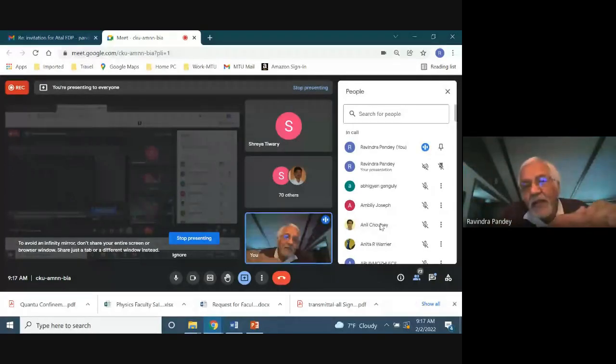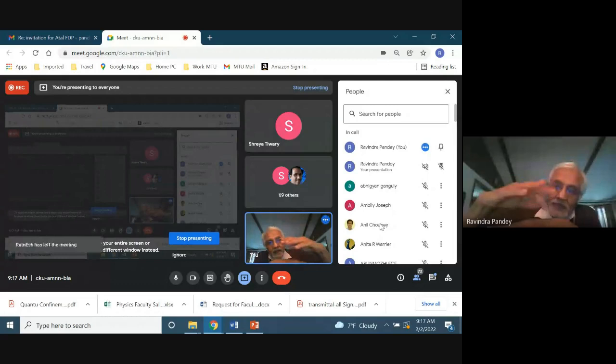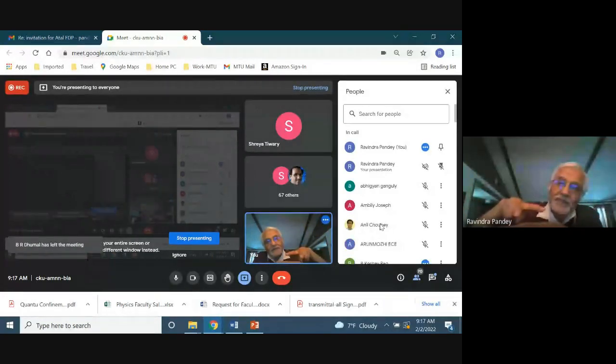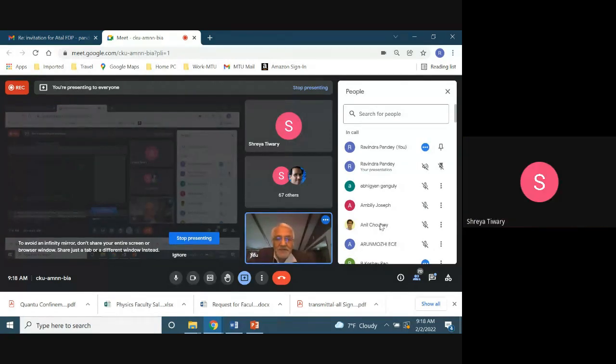And for graphene, being carbon again, in the monolayer you're going to have a zero gap, and BN has a finite gap. When you combine them together, there is this electronegativity difference, or difference in bonding. One carbon is looking at boron, the other carbon is looking at nitrogen, so they experience a dissimilar electronic structure. They're going to behave a little differently, which induces a small gap in graphene. So your electronegativity argument reflects in the band gap, or in terms of the current. Got it, sir. Thank you, sir.